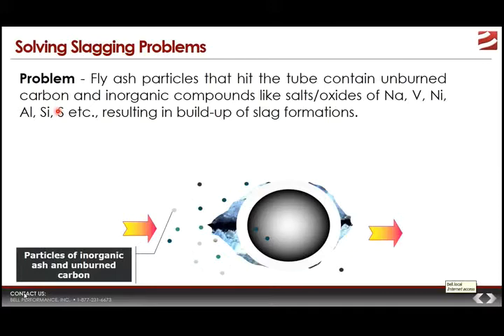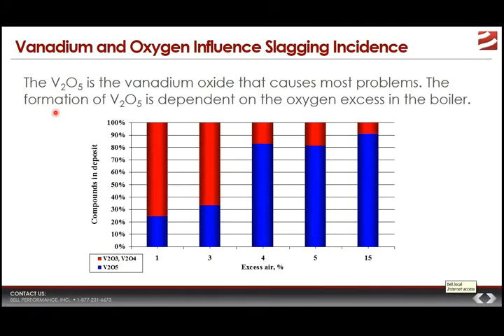Now, slagging can be influenced by things like combustion conditions in the boiler. It can be influenced by fuel composition. It can even be influenced by the composition of the alloys themselves. All of these together will influence slag formation, the rate of buildup of slag, and the corrosive nature of such deposits. So when you talk about fuel composition, the vanadium content of the fuel directly impacts slagging problems.